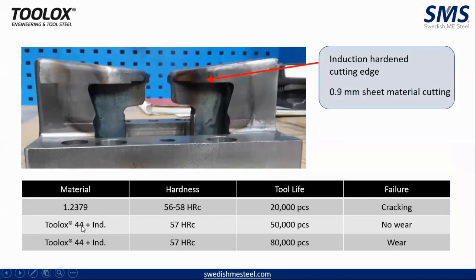Then Toolox was used as a replacement. Since the sheet thickness was less than 3 mm, Toolox 44 plus induction hardening was used. Hardness was 57 HRC, 50,000 components, no problem. And at 80,000 components, you have a problem of wear, but not the problem of cracking. So if you have any area where cracking is your issue in any of your tooling requirements, then Toolox can be an immediate substitute for that.